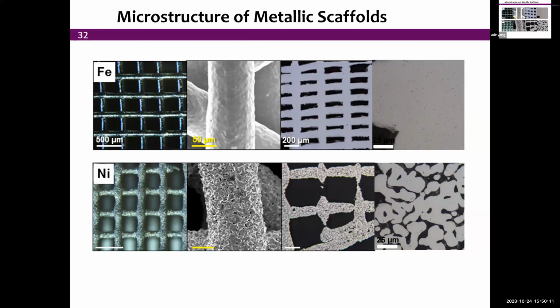So here is a good example with iron. As you zoom in, this is a cross-section, this is the SEM with solid, and the cross-section here shows barely any porosity. This is a 25 micron bar. On the other hand, nickel is now highly porous, and you can see pores in the surface. It's actually open, right? So this would be a very nice structure if you're interested in catalysis and a very high surface area, while still maintaining an architecture for the catalyst.